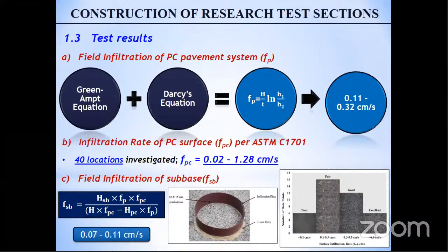Based on this test, the pervious concrete layer was segregated into several sections, which were designated as poor, fair, good to excellent, as can be seen on the bottom right side of the screen. Now, for the excellent test sections, where the permeability rate was higher than 0.5 centimeters per second, just for your information, I want you to know that some of these stretches gave us permeability values even as high as 1.3 centimeters per second, which is actually a very good number.